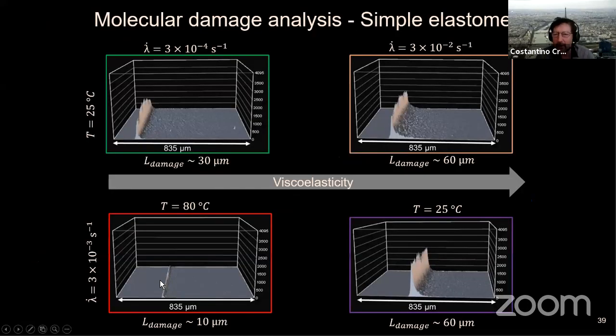Now, if we look at the molecular damage, the raw data from the confocal microscopy, you can see that the rate has a moderate effect, but has an effect. This is low rate, high rate. And at the bottom, you have the low temperature on the right and the high temperature on the left. You can see that at high temperature, the amount of bond scission is much, much less.